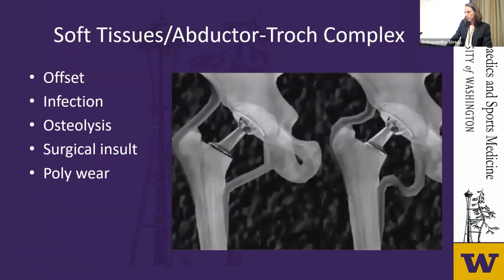Soft tissues and especially abductor deficiency is a huge problem in total hip. Inappropriate tension on the abductors can be due to several things, which includes technical errors with implant selection, injury to the troch. It can be due to sources of inflammation causing damage or changes to soft tissue, including infection or osteolysis. And then longer term, you can see gradual medialization and shortening due to polywear. The treatment for this includes modular exchange with head, neck, and liner exchange, and addressing the abductor mechanism with either repair, reconstruction, or trochanteric advancement, and then possibly the use of constrained liners to help mitigate some of that laxity.